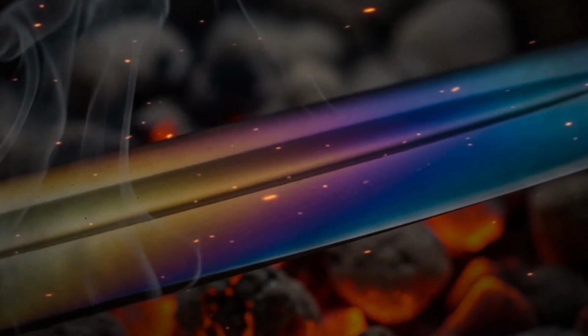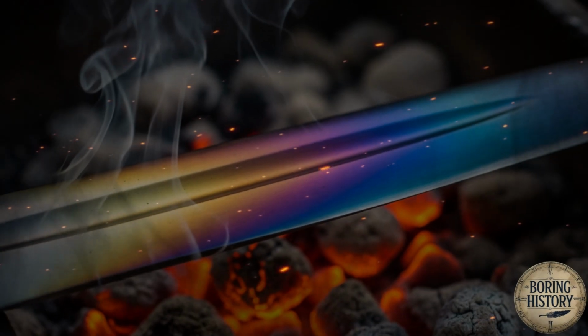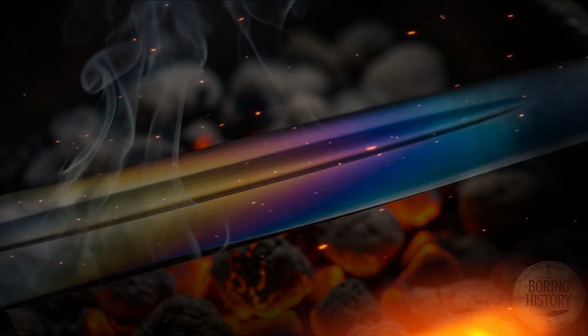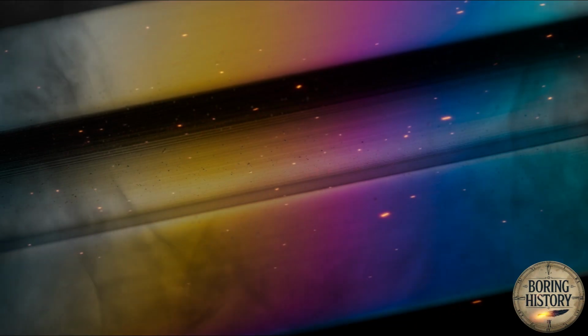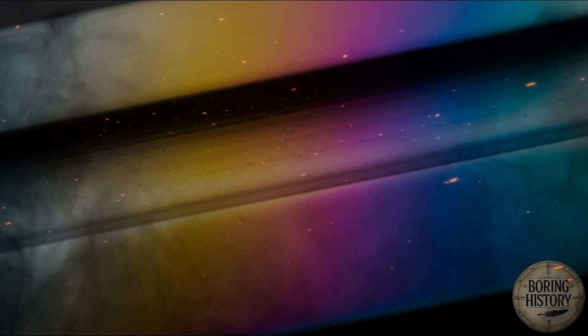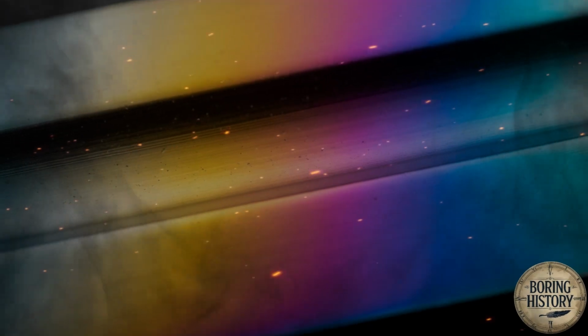"The welding itself is the same process as before, but the materials are different and the heat management is more critical. Crucible steel and pattern welded composite have different optimal welding temperatures. They overlap. There's a range where both can be welded, but the range is narrow and the price of getting it wrong is a cold shut in the most important location in the entire blade." Sigrun nodded. The edge. If there is a cold shut in the edge of this blade, the blade is not an Ulfberht. It is a sword. A good sword, perhaps a better sword than most, but not this.